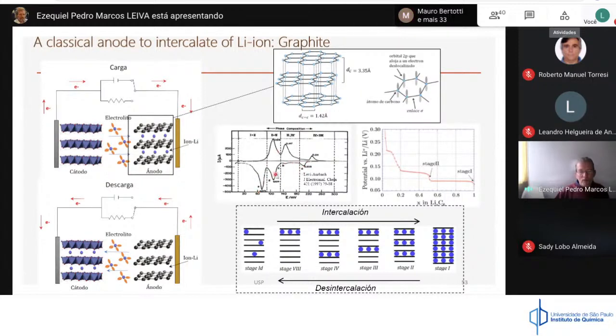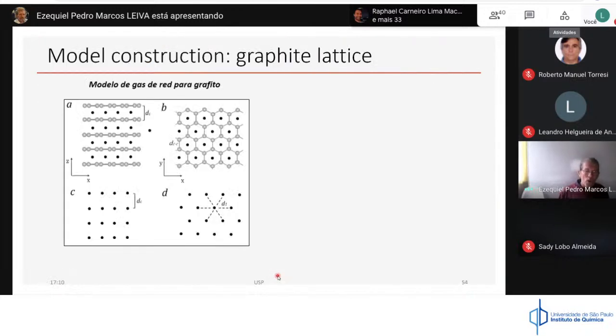These processes that you can find in the voltammogram are related to some stages. And these stages are different lithium layers, which are separated from other lithium layers in graphite by a number of empty layers. So as intercalation proceeds, you get layers which are coming closer. As they intercalate, this comes in this sequence. So this was an interesting system to simulate. We constructed a graphite lattice.